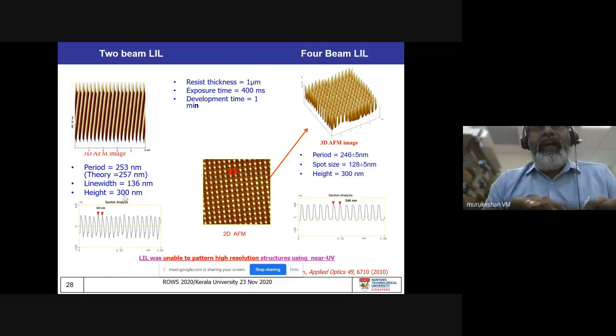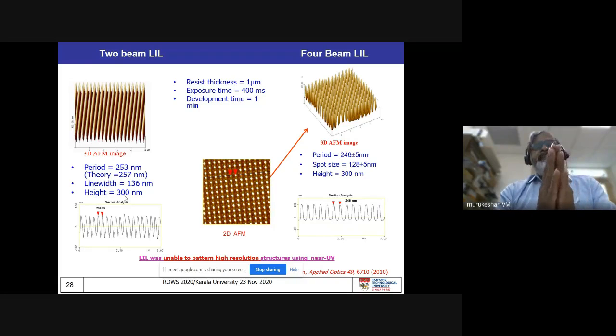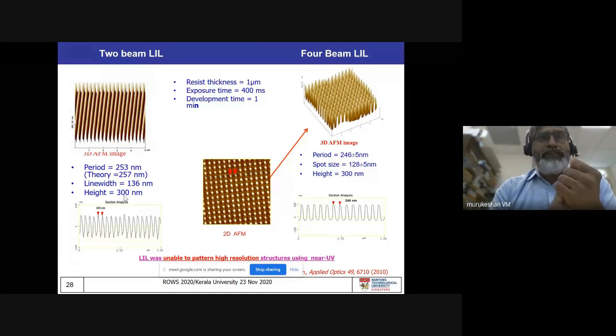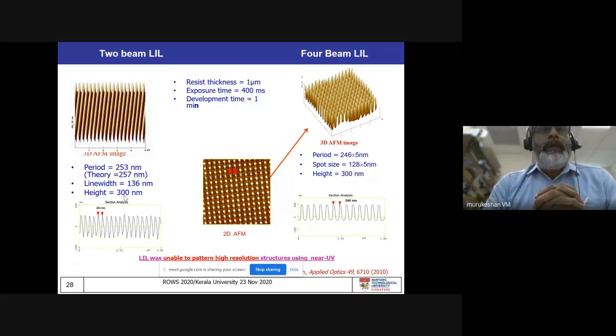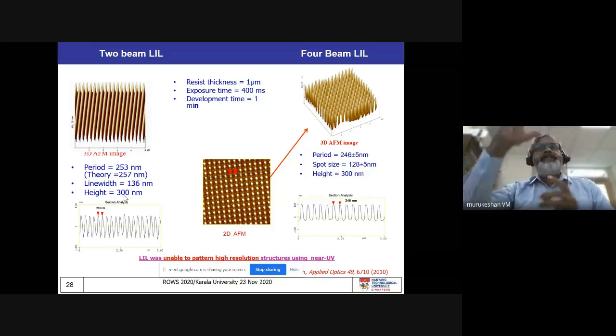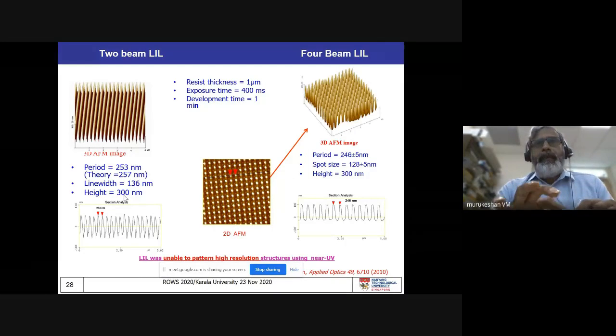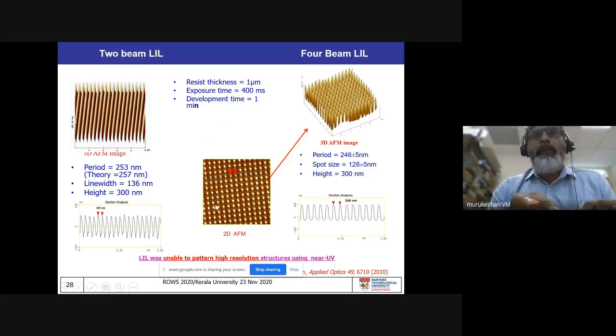300 nanometers approximately the height. So aspect ratio is also very important, because for the semiconductor fabs, when they give us the problem, they want not only line features, they also want some contact pillars also. So we're also looking into the aspect ratio, that is the height to width ratio. And we found that when we use 4 counter-propagating beams, we were able to get this nice pattern.